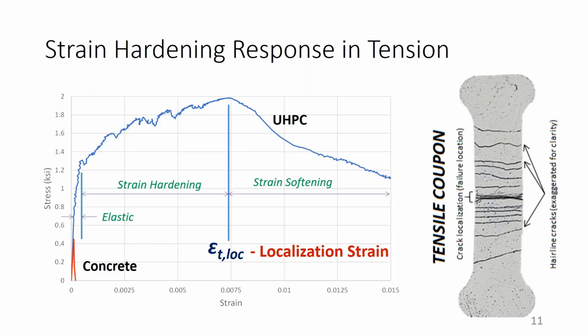However, as you keep loading it, inexorably, one of the cracks, the fibers there, for some statistical reason, will not be able to support the load. They will start to slip out. And when that occurs, you basically go into the softening regime. So first is the elastic strain hardening, which is quite extended, as you can see, and then strain softening. The transition between the strain hardening and strain softening is called the localization strain. So please remember this word because I'll be using it quite a bit later on.